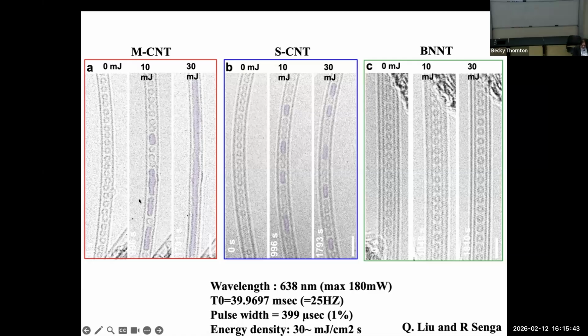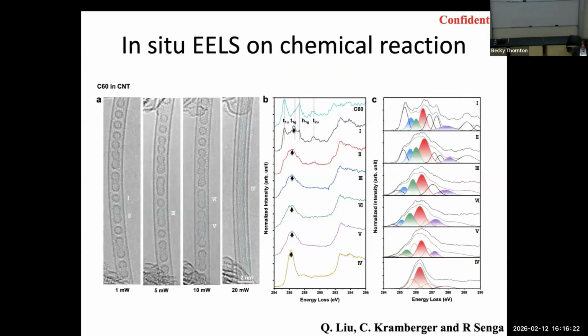And for the metallic nanotubes, as I told you, you have exactly the same band gap at 1.94 eV, so it can excite the reactions. For the semiconducting tubes, the reaction happens very slowly. But for the boron nitride, it doesn't happen. So it means we can control the reaction happening inside the nanospace, because each nanotube has a different band gap. If you choose the right laser, you can activate certain nanotubes.